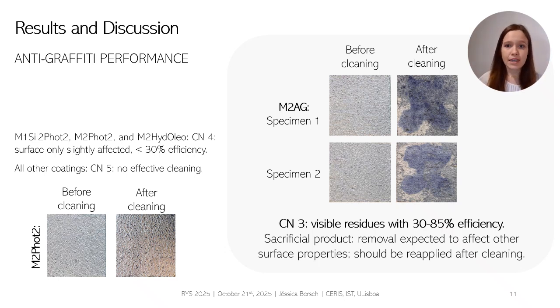Regarding the other systems, only mortar 1 and 2 applied with the photocatalytic coating 2 and mortar 2 with the hydrophobic and oleophobic coating showed a CN4. It represents that their surface was slightly affected by the cleaning process with an efficiency lower than 30%. They are also illustrated with images. All the other coatings got a CN5 class, that is, they did not present effective cleaning.